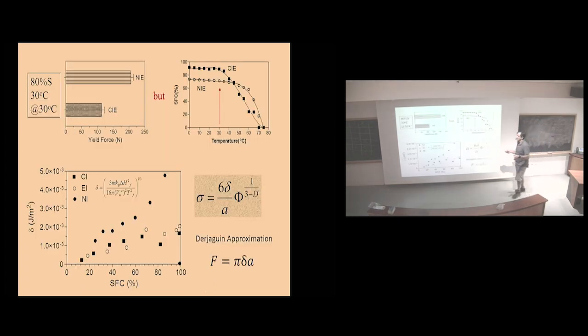So, what happens when you interesterify? Let's take the example of chemically interesterified and non-interesterified, 80% solids. When you actually do a yield force, cone penetrometry, hardness of the material, you find that the chemically interesterified one is softer, has a lower yield stress. So we start there. So you go, oh, obviously it has less solids. However, in the range where we measured at 30 degrees, the chemically interesterified has more solids. So it's softer and it has more solids? What the hell?